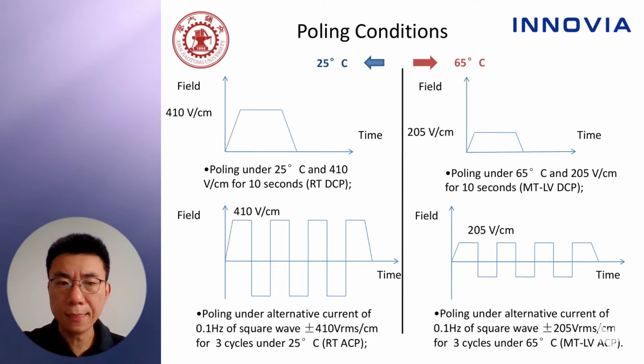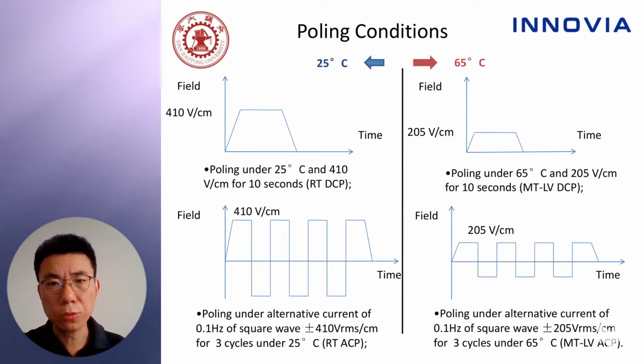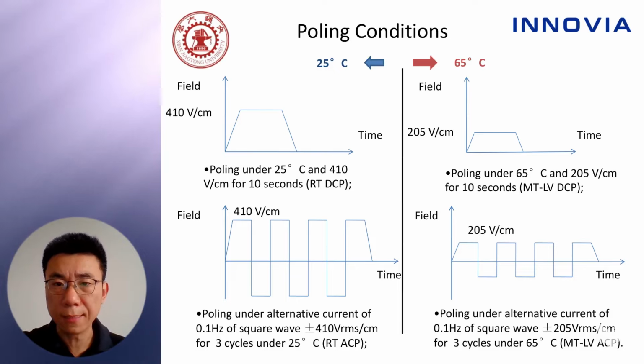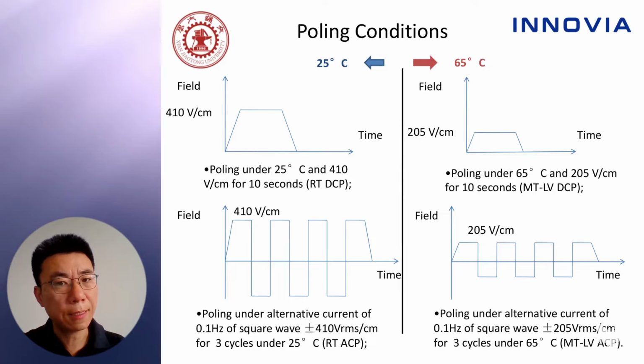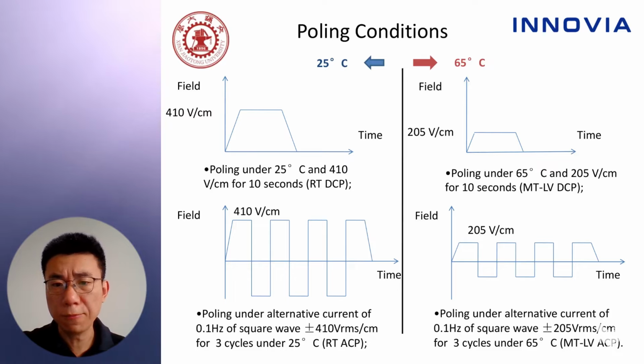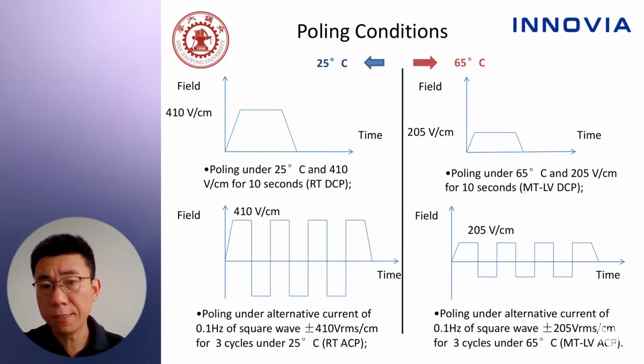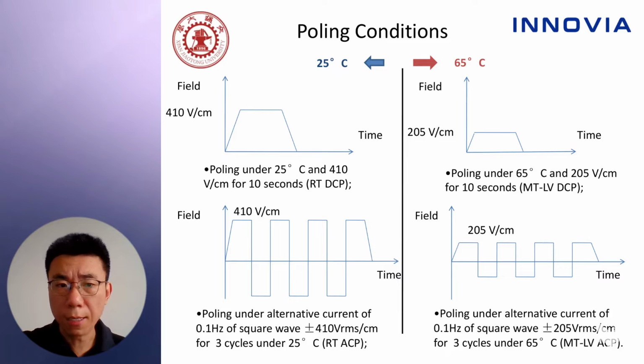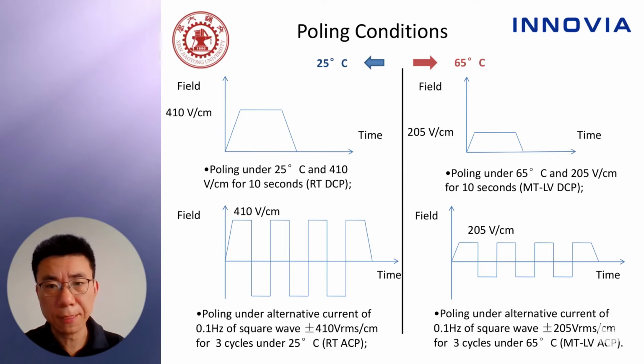We call it RT-ACP. Moving to the right side of the screen, poling at 65 degrees C and 205 volts per centimeter for 10 seconds. We call it MT-LV-DCP. And then poling with an alternating current of 0.1 Hz square wave plus minus 205 volts per centimeter for 3 cycles under 65 degrees C. We call it MT-LV-ACP.